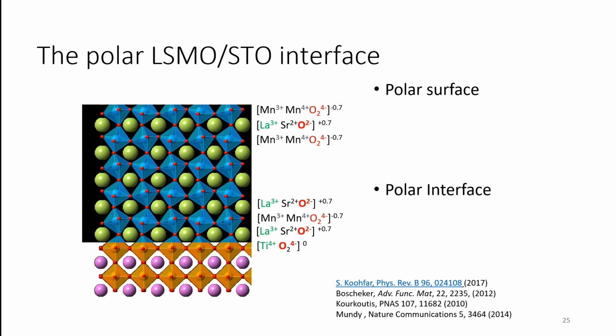So going back to the structure, if we actually look at the structure of LSMO, it's very similar to the LAO-STO case, where each plane here has some net charge. And for this particular composition, it's going to be a plus 0.7, minus 0.7 stacking in the vertical direction. If you terminate your material, which we can do pretty well, for example with manganese oxide, then the layer at the top here has a net negative charge. So here you have a charged surface, a polar interface if you grow it on strontium titanate. And there might be some reconstructions which might occur here, which in this particular case are leading to the dead layer effects, whereas in the case of LAO-STO, they're leading to Science and Nature papers.